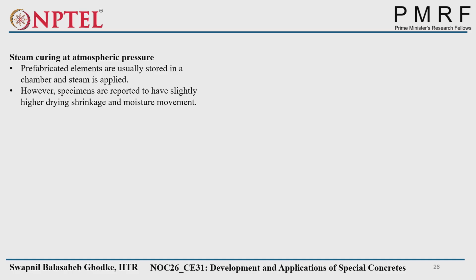When you go with steam curing at atmospheric pressure, prefabricated elements are usually stored in a chamber and steam is applied at atmospheric pressure. But there is an observation that slightly higher drying shrinkage and moisture movement occur at atmospheric pressure. Moisture movement is the movement of moisture from the concrete surfaces or concrete matrix. As the moisture moves, the movement of water causes the drying shrinkage.